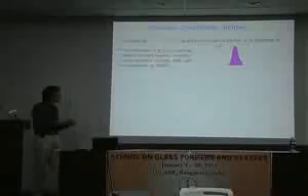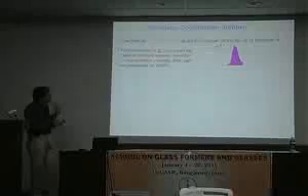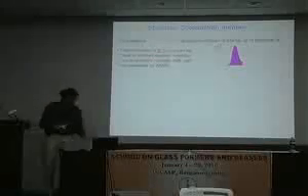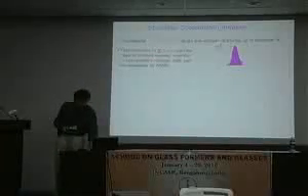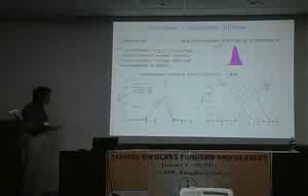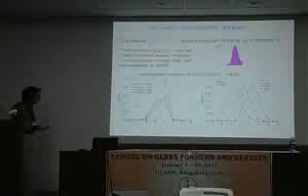And this quantity can, for example, be measured in NMR experiments in a bit indirect way, but some people, I trust that they actually can get out real numbers. So this is a quantity that is integral, but it gives you some information on how the local structure of the system is organized locally. And again, just to give you an idea of how this quantity looks, here this is the probability that a silicon atom has Z other silicon atoms around it, and this is for different types of systems.